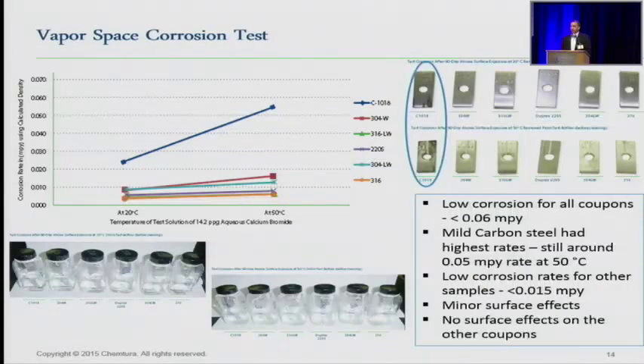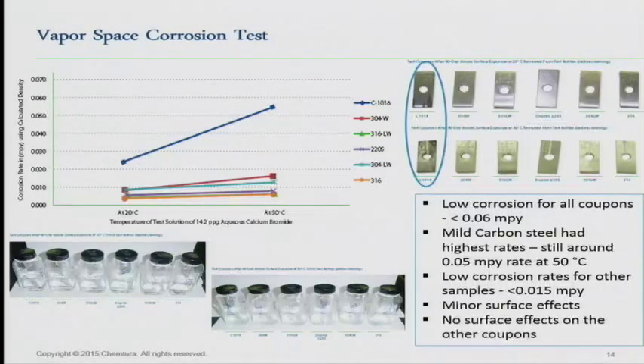If you look at the vapor space, virtually no corrosion. Again, we're not at temperatures here that are going to do a lot of things to break this down and get a lot of HBr production. But for the most part, if you're just talking about the front end of your system, where you have a calcium bromide tank, where you're adding it to your belts or doing something like that, calcium bromide is not really showing to be a big issue as far as corrosion up to 50 degrees C. And you can see there the solutions were very clear. The coupons looked very good.